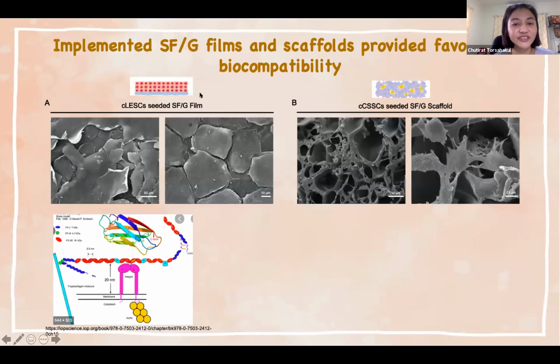And the next part is the SEM analysis of the cells on the film and the cells in the sponge-like scaffold. Corneal limbal epithelial stem cells on the film can form a stratified layer of about 2 to 3 layers. And the cells in the basal layer look smaller than the cells in the upper layer. And for the corneal stromal scaffold, the cells can penetrate into the pores and can secrete extracellular matrix.